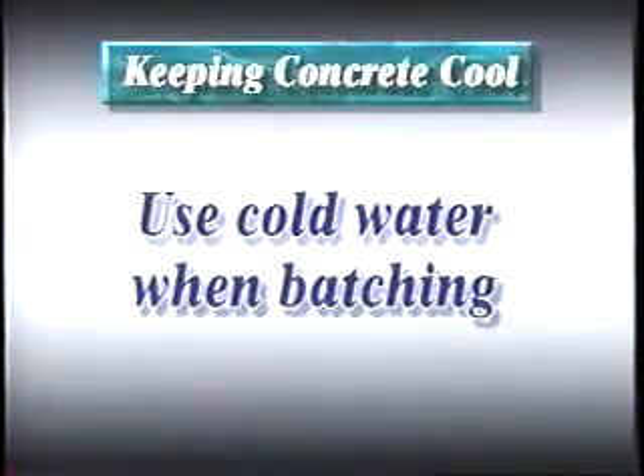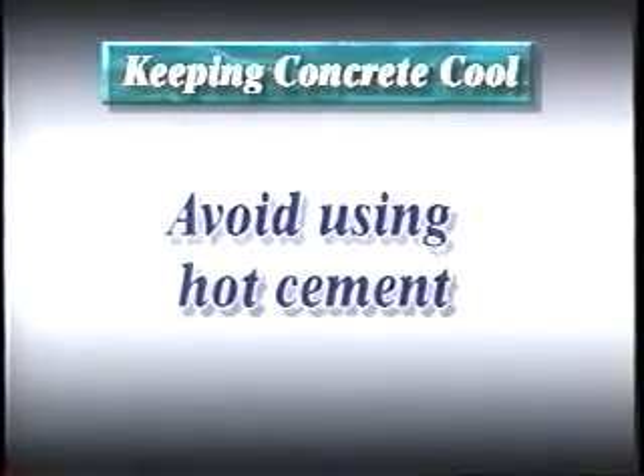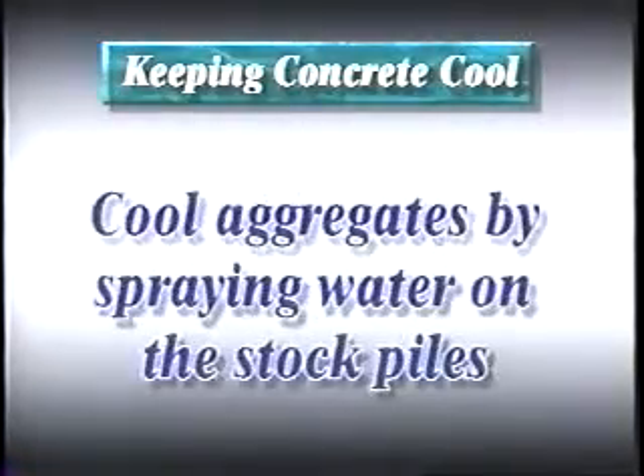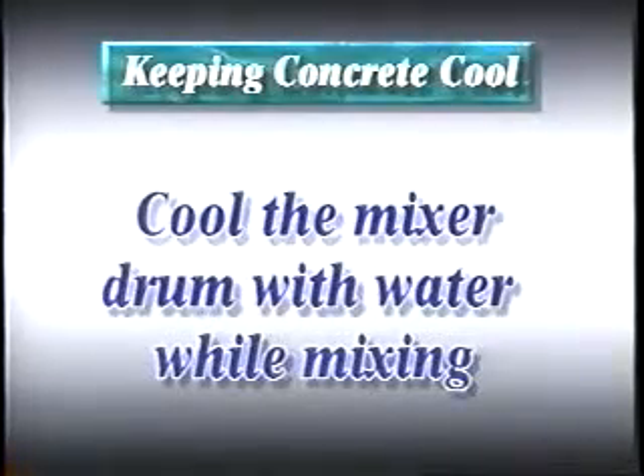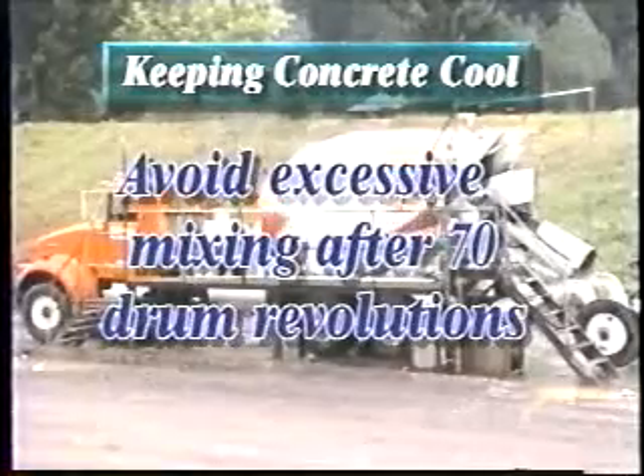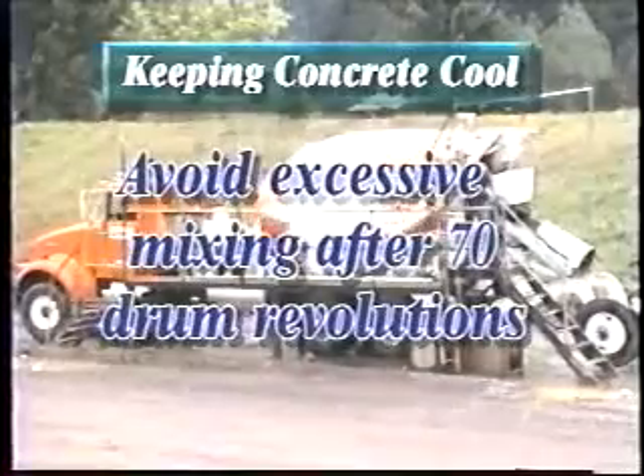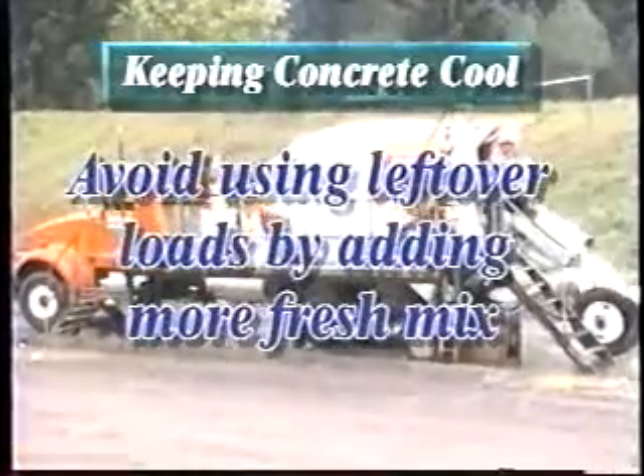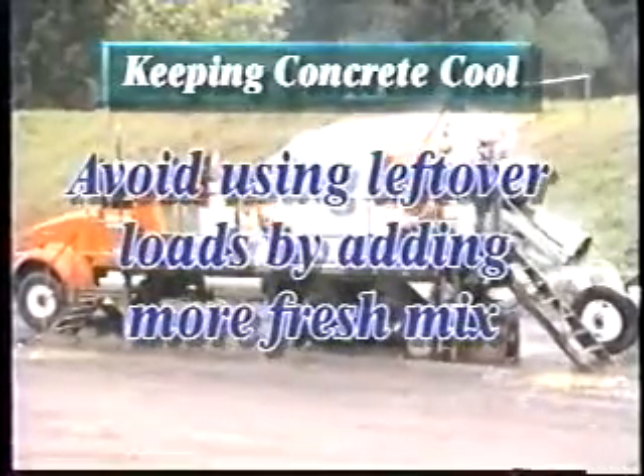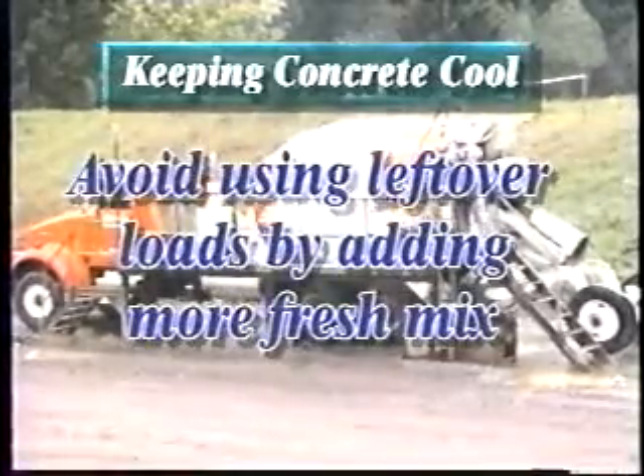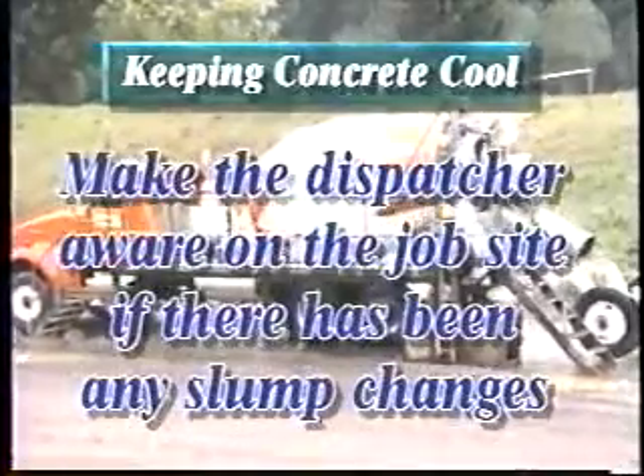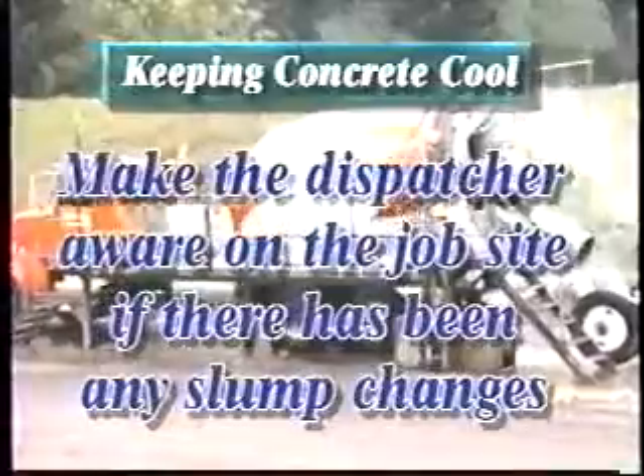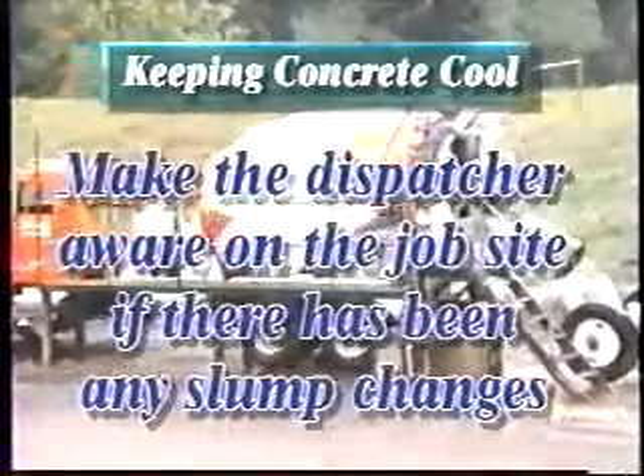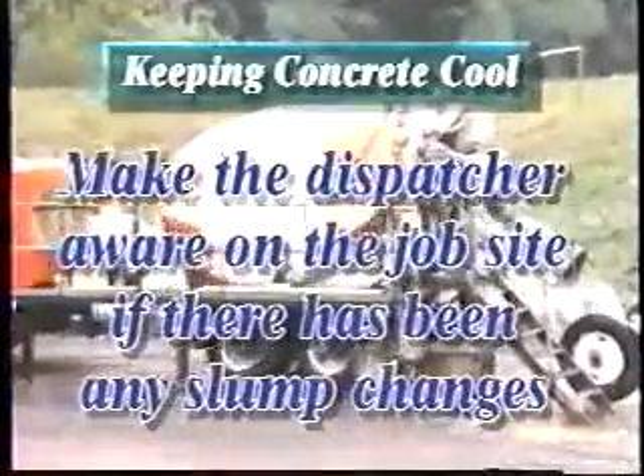Use cold water when batching. Avoid using hot cement. Cool the aggregates by spraying water on the stockpiles. Cool the mixer drum with water while mixing. Avoid excessive mixing after 70 drum revolutions. Avoid using leftover loads by adding more fresh mix to the load to create a full load. Make the dispatcher aware on the job site if there has been any major slump change so that mix adjustments can be made. Now,